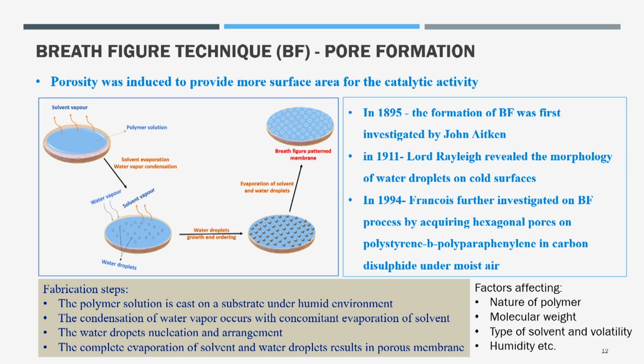Initially, on the left hand side, she made a film. She dissolved polylactic acid in a suitable solvent, and then she spread it over a base, so the film is made. The solvent was not dried initially; she made the film with the solvent. Then she kept it in a humid system. Humid system means the atmosphere contains a lot of water. Now, what two processes operate?